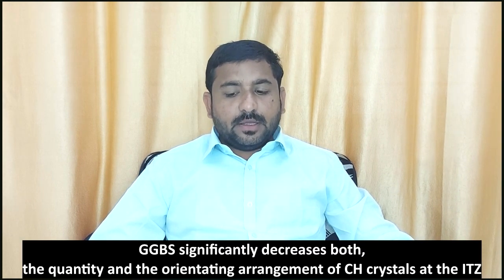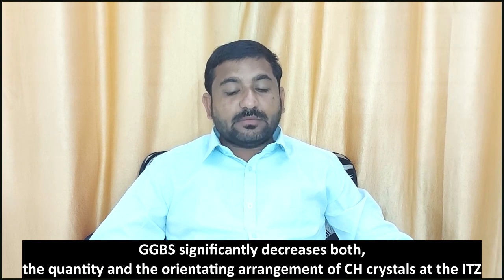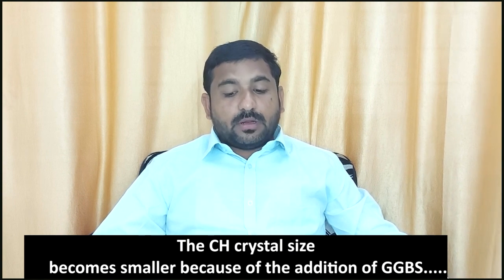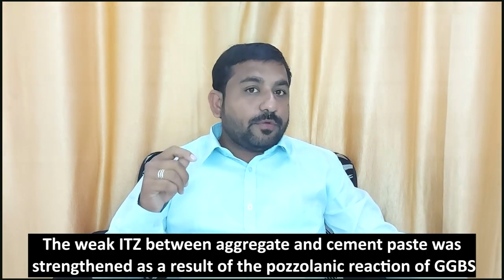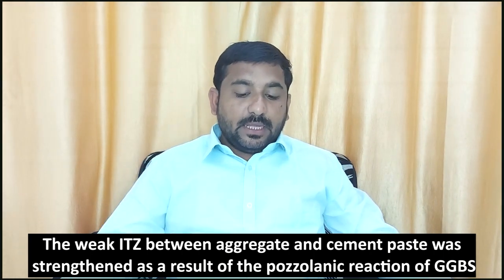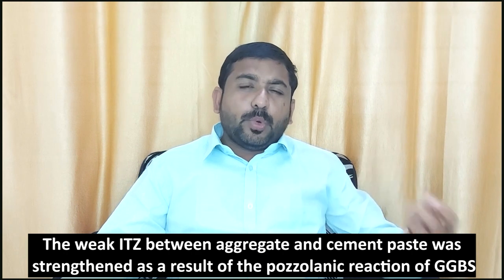Now coming to the third point, ITZ, the interfacial transition zone. It has been demonstrated in many trials and researches, you can go through them, that GGBS significantly decreases both the quantity and the orienting arrangement of calcium hydroxide crystals at the ITZ. The crystal size becomes smaller because of the addition of GGBS, and when the GGBS is ground fine, like more than 450, 500, 600 square meters per kg, the GGBS improves the ITZ.